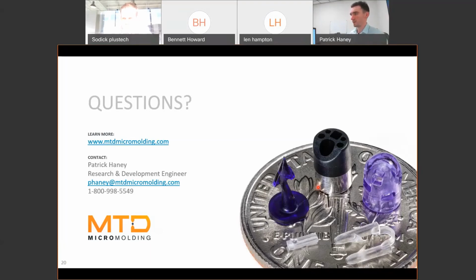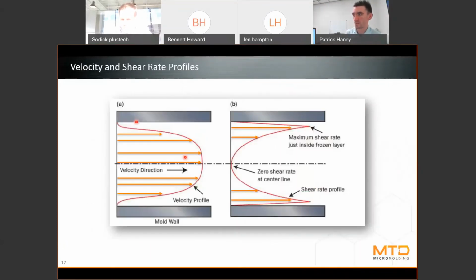So back here when I brought up the shear profile, if we imagine this to be flat, and then this to still have a similar influence as it does at regular flows, then we might have an extra amount of heating here, an extra amount of orientation here, or something like that. So certainly, I think tunnel flow would occur in any scenario, whether it's a large channel or not, where your laminar velocities in principle are near, if not equal, right? And then your shear rates, this profile won't change to the same degree that this will. So tunnel flow is certainly more influenced by figure B here, the shear rate profile.